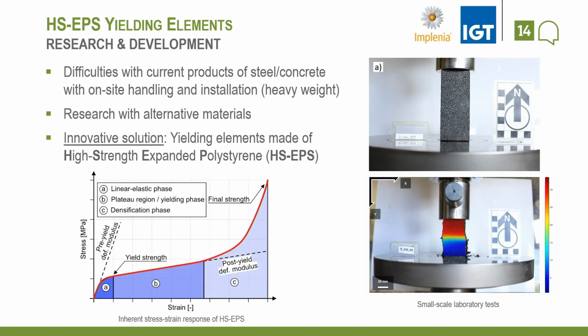This type of material has an inherent stress-strain response. It consists of a linear elastic phase, a long yielding phase in the central part, and finally a densification phase. And this was exactly what we've been looking for.